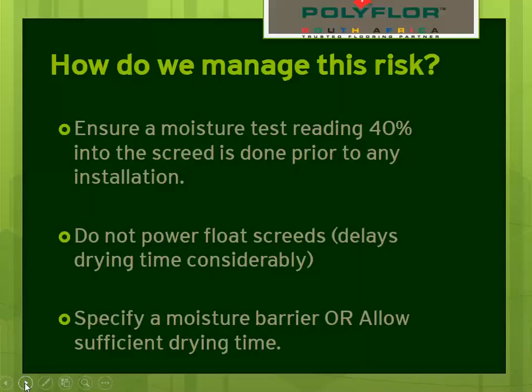Preferably do not power float or burnish the screeds, as this significantly delays the moisture evaporation. If the screed has been power floated, grinding it to open up the surface will assist in speeding up the drying process. The ultimate solution is always to specify a suitable moisture barrier.